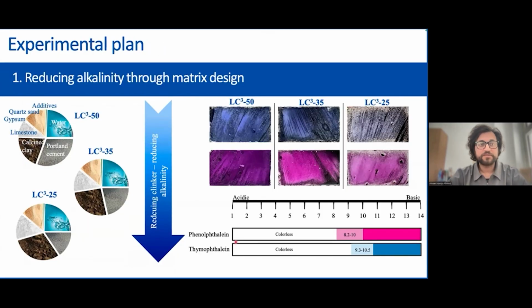First, we can reduce the alkalinity of the matrix. This is, let's say, the most obvious way to go about it. Since the matrix alkalinity is closely linked to the Portland cement content, what we did in our study is systematically start reducing the clinker content in the matrices. And here you see the three design matrices. I will show in the upcoming slides how PET performs in these three matrices.